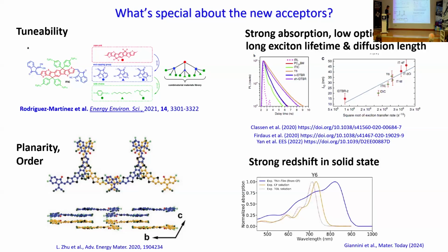Another important thing is if we look at their optical spectra, you tend to see a very strong redshift in the solid state compared to in solution. And that's a signature that there's quite strong electronic coupling between the molecules, leading to delocalized excited states. So we expect that there should be strong coupling between different molecules.